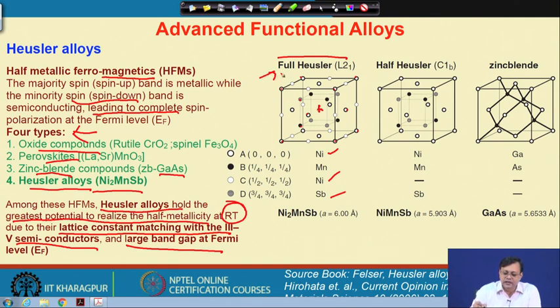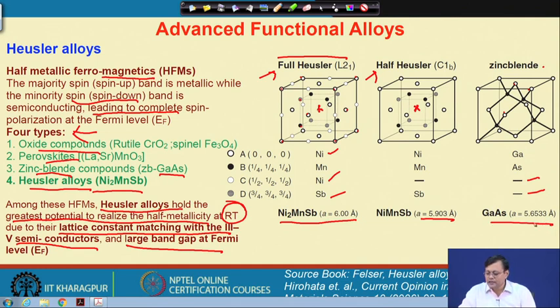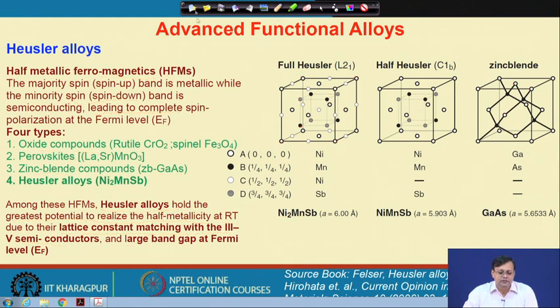Now, the difference between full Heusler and half Heusler is that the C sublattice is vacant. So, here C is at the center, that is vacant, where nickel is supposed to be, and therefore there is the presence of nickel, manganese and antimony. In case of full Heusler, it is 6 angstrom lattice parameter. In case of half Heusler, it is 5.9, and in case of zinc blende structure, this is also an Fcc based structure. However, both the C and D sublattices are missing. Okay. So, zinc blende structure is very famous for gallium arsenide, and it has a lattice constant of 5.65 angstrom. And these 3 different compounds, or these half metallic ferromagnetics, show very interesting properties.